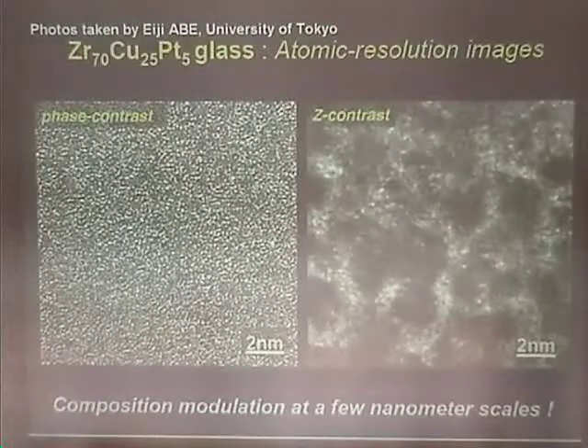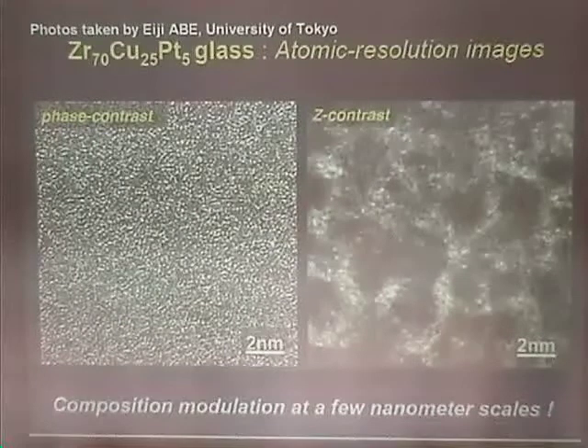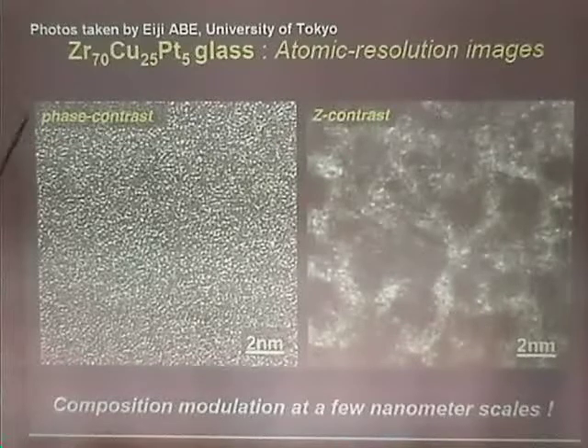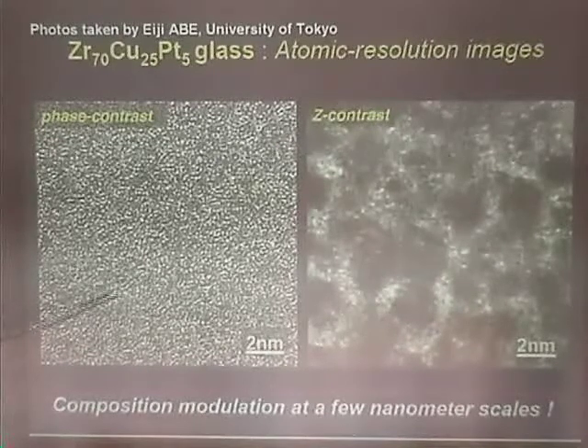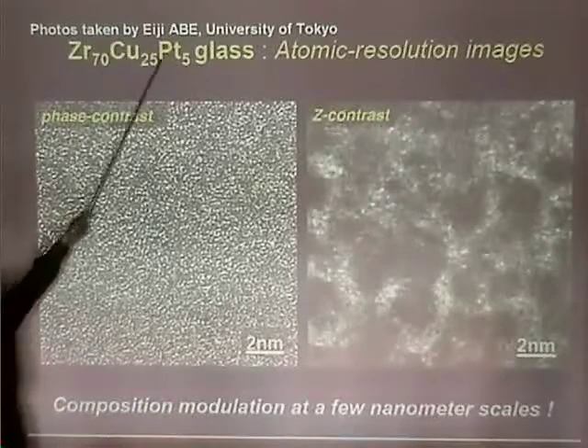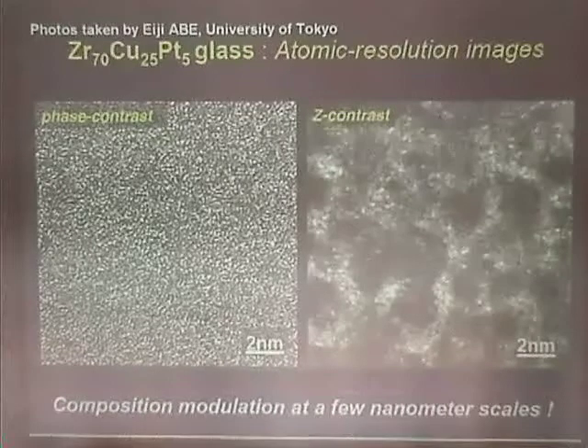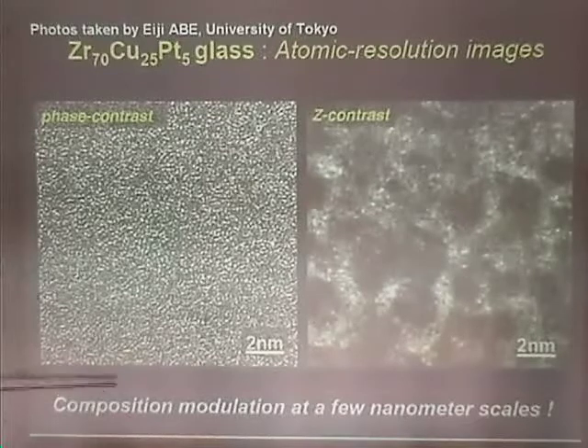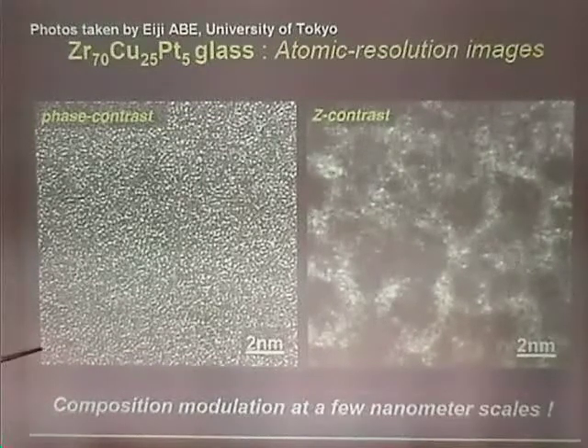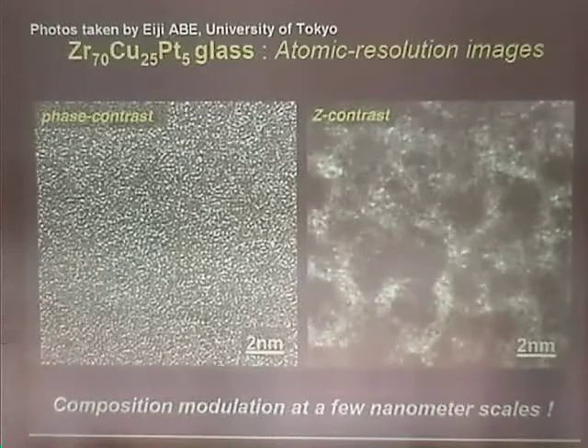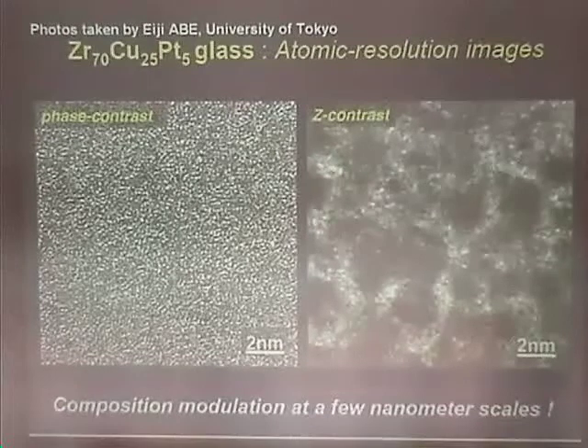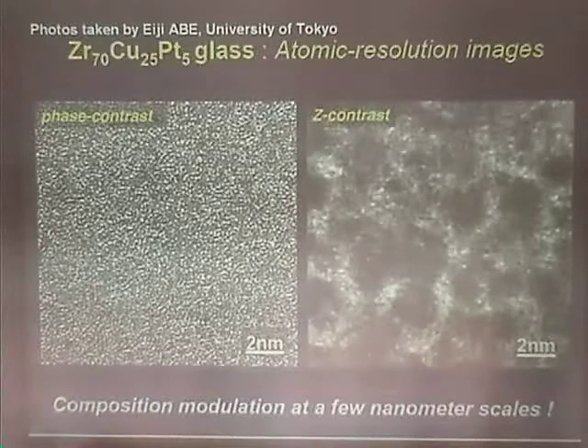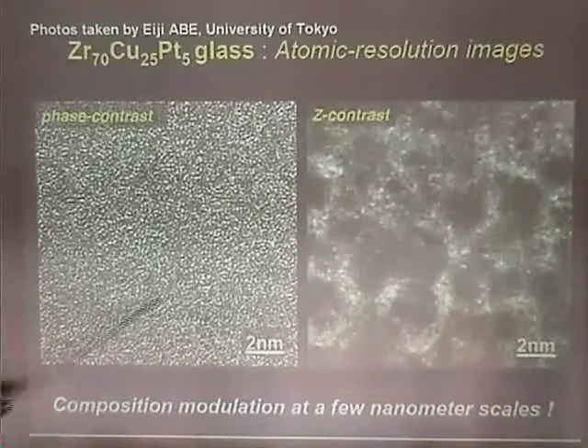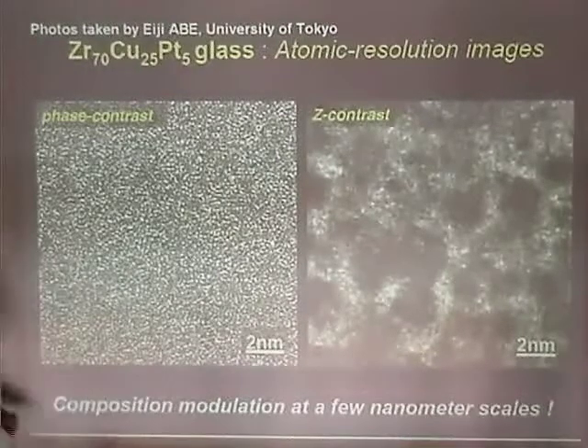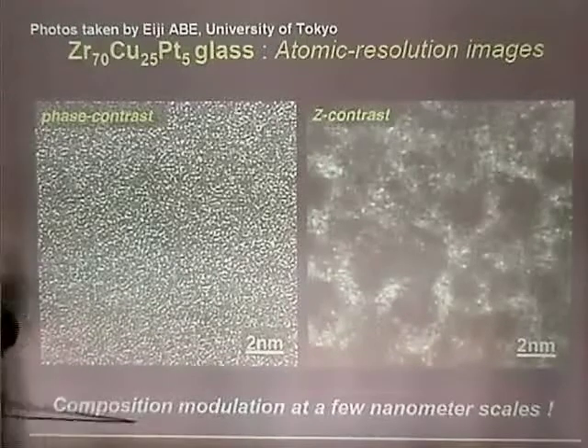And recently, this is not my collaborator, but this picture was taken by Professor Abe of the University of Tokyo. Usually it is only phase contrast, and amorphous alloys show this maze contrast only. But he uses scanning STEM and the HAADF method. He successfully observed compositional modulation at a few nanometers in zirconium-based metallic glasses, like this figure.